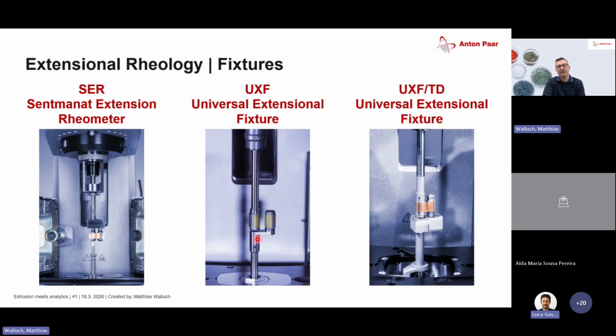For a universal extensional fixture, this is something that was designed by Anton Paar. We only have 1 drum that rotates. So here this drum rotates, here the sample is just fixed, and here we stretch the sample and get the same data. The benefit of this system is that we can also do oscillatory measurements because we don't have any gearboxes, and therefore we can do some basic DMA as well using this. And then we have the UXF twin drive, which is basically the same like the SER tool. Here we need a second rotational drive, and we also rotate both drums and stretch the sample, and we get basically the same data like with the SER tool.